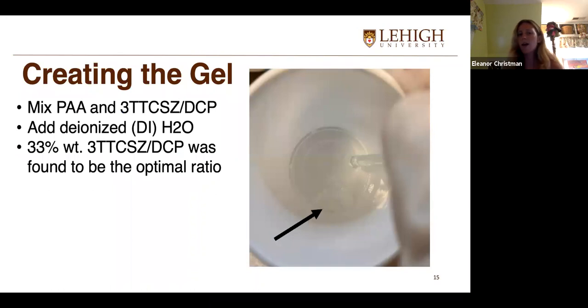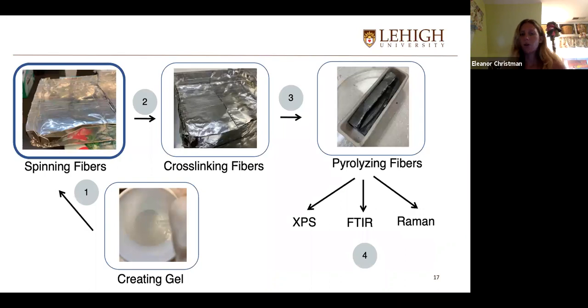So I mixed PAA and 3TTCSZ/DCP. And I found that after experimenting with the ratio that the 33% weight ratio was definitely the best ratio between these two. And I also found that I needed to add some DI water to create this gel and also to allow myself to add some drops of water while spinning the fibers to ensure that the gel didn't dry out too much. So next I'll go on to spinning the fibers.